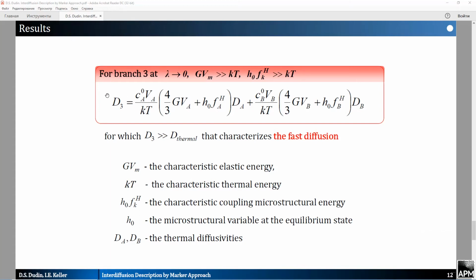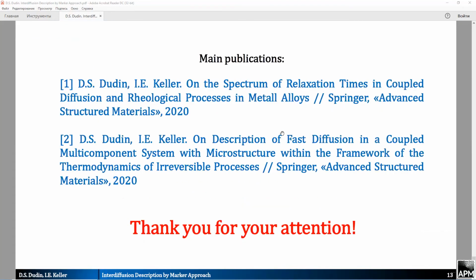Interdiffusivity D3 has the following features. First, it significantly exceeds the usual thermal diffusivity. And secondly, a prerequisite for obtaining this diffusion coefficient is the assumption of a fine-grained structure. These features are completely consistent with the experiments that I mentioned at the beginning of the report. Thank you for your attention.